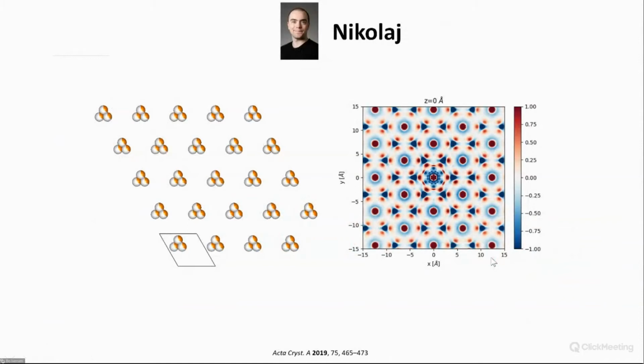Now, Nikolai then said, okay, can't I solve the structure? He said, I can use my 3D PDF. If I choose an origin, then of course I'm autocorrelated with myself. But then I'm negative just around. That's, of course, because if the copper atom is here, then you can't have two atoms here in the disordered structure. So the true structure must have just one copper atom. And then you could look at the vectors here. Can I have a copper atom here? But it's negative. That means that there's less density than in the average structure. So that's not where the copper is.